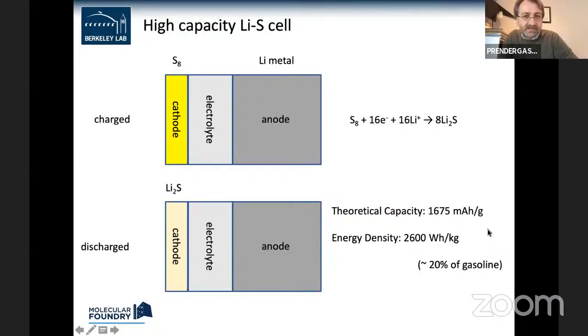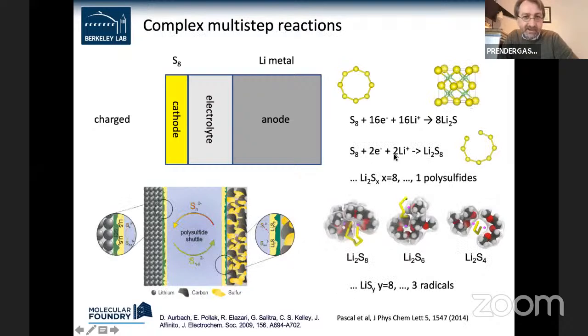Lithium sulfur is a complicated system. You're converting sulfur to lithium sulfide. There's 16 electrons and 16 ions involved. Obviously, that's not a single step reaction, and it involves the breaking of the sulfur ring in solid sulfur as it becomes reduced and forming various what are called polysulfides. So they have the formula Li2Sx, where x could be anything from 8 down to 1. And you can also form radicals with only 1 lithium. So they're also complicated chemistry.